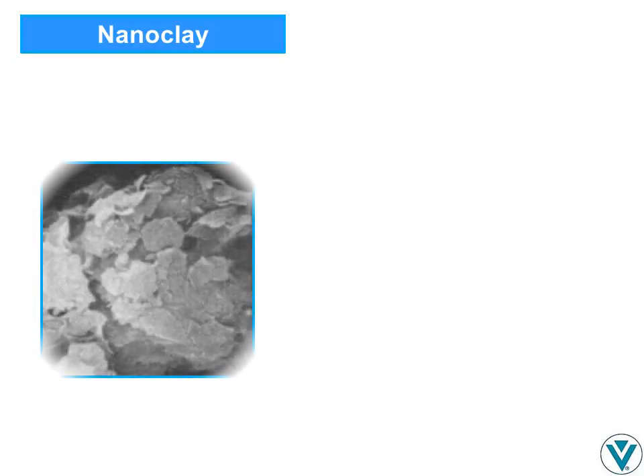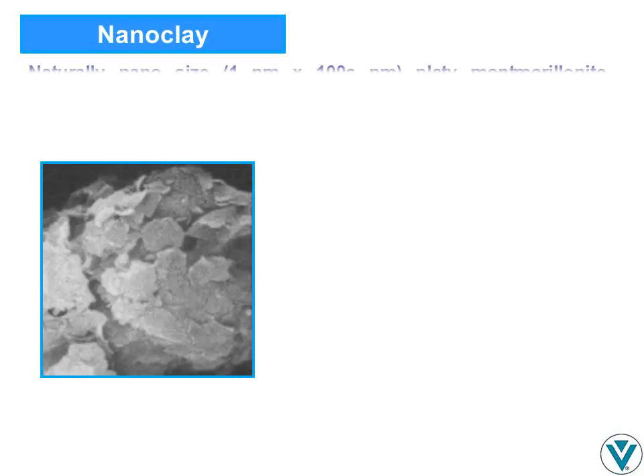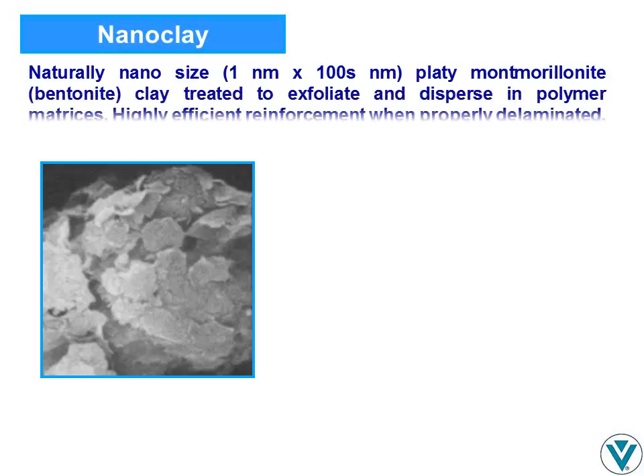Nanoclay, also known as organoclay in other industries, is made by reacting an aqueous dispersion of montmorillonite with a cationic surfactant, for example, a fatty quaternary ammonium compound. The surfactant replaces the alkali or alkaline earth cation that naturally neutralizes the anionic charge of the clay lattice, making the clay hydrophobic and oleophilic. The resulting nanoclay is filtered and dried.